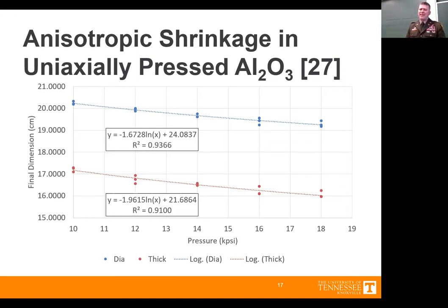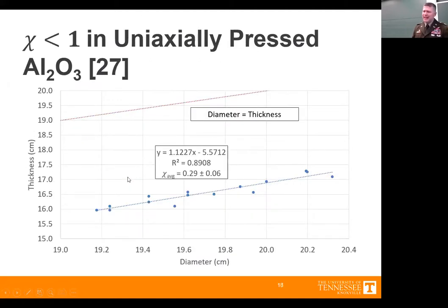And what they saw was that there's this trend that the more pressure that was applied, you know, obviously the more it shrank in the axial direction. But also, no matter what, there was this inconsistency, this gap between the shrinkage that they saw in the axial direction versus the radial direction. And so on the next slide, I take that same data and I plot this chi value, so the ratio of delta R to delta A, versus, you know, the ideal situation that shows isotropic shrinkage. So if it shrank the same in both dimensions, it would be along or very near this dashed red line, which is isotropic shrinkage.